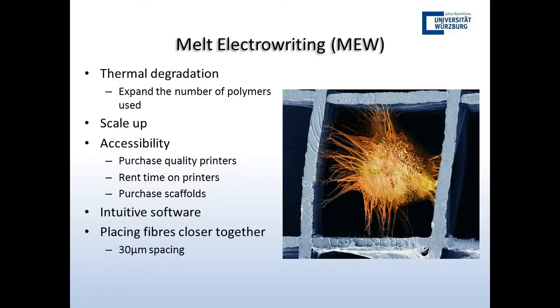For challenges in the future, thermal degradation is a big one. It's not a big issue with PCL. PCL is lovely, 60-degree melting point, hydrophobic, doesn't have a lot of water going into it, but PCL is not the only one. It's a great material because it's useful for in vitro and in vivo, but there are other polymers out there that have different properties that you'd like to explore. Thermal degradation is a big issue with most of them.